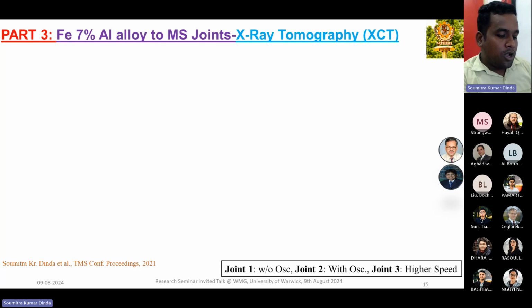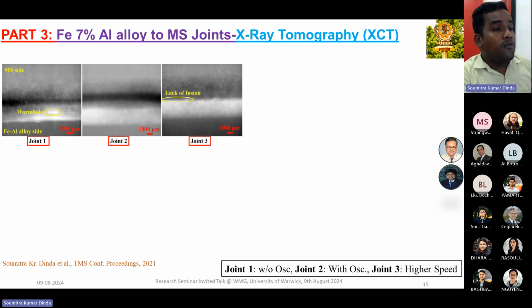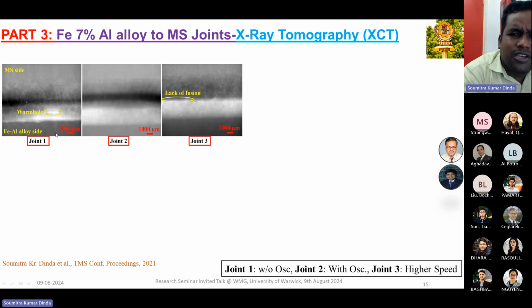Now, before going to X-ray tomography, we first did the X-ray radiography. Using the same machine, we scanned the whole sample. We can see visible wormhole or lack of fusion type defects, found in joint 1 and joint 3 respectively. The wormhole is just agglomerated or accumulated pores, accumulated in one place. And lack of fusion means lack of penetration, which may be due to high welding speed or some other inappropriate welding condition.